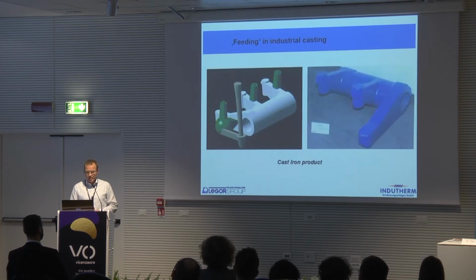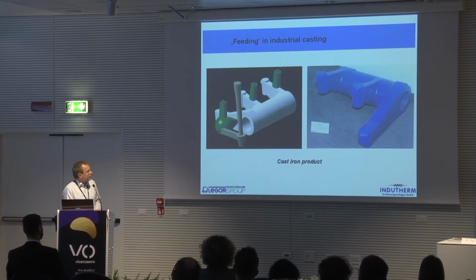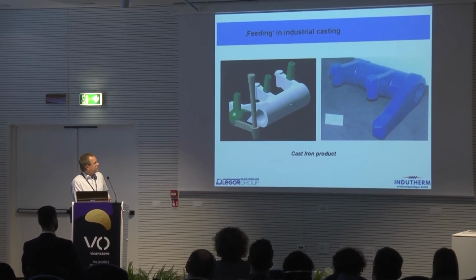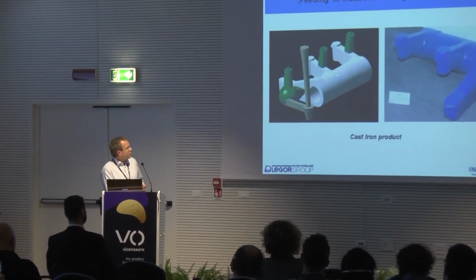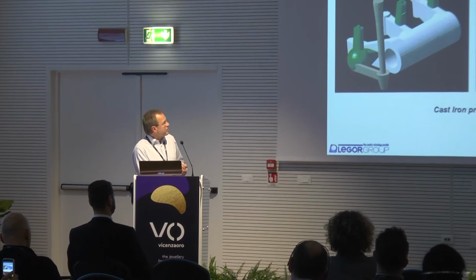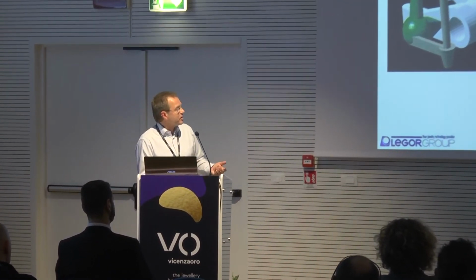So how is this done in practice? In industrial castings, like you can see here, this is the cast that's going to be cast. And you see these green items here. These are feeders that are put on typical sections of the cast part, and they will supply molten metal to the casting and feed the casting with liquid metal during all the process to avoid shrinkage porosity.